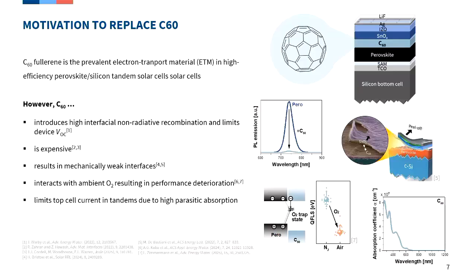You do see photoluminescence quenching. That means your solar cell, or let's say your perovskite, if it is in contact with that material, doesn't emit light—it's not a good LED anymore, and then it's also not a good solar cell anymore.